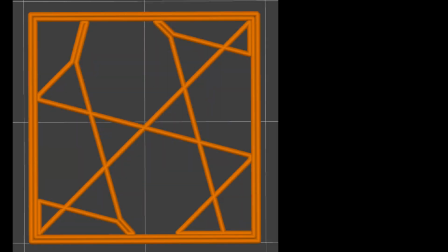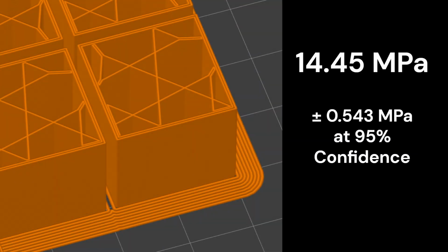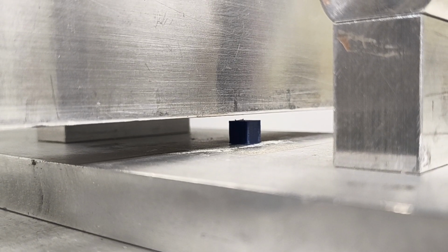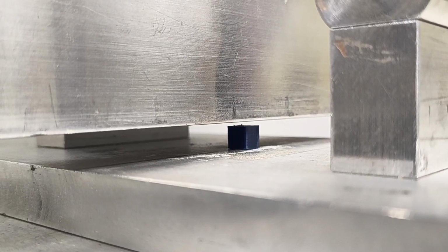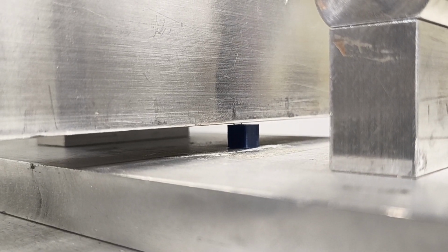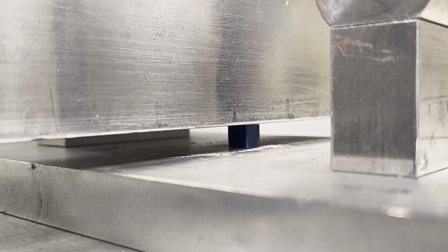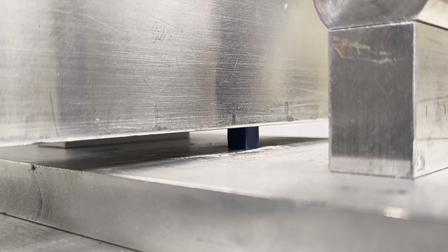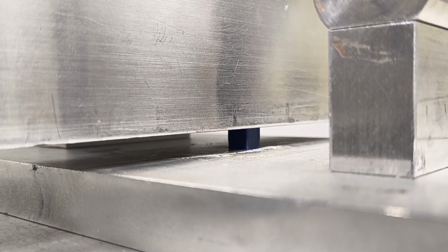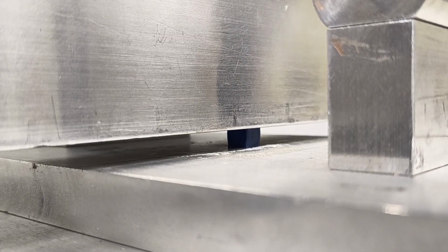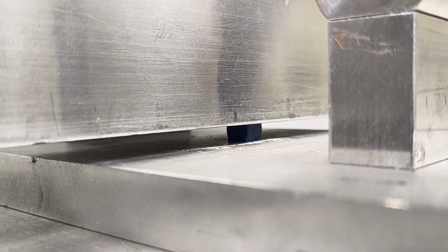Our results showed that the trihexagon infill pattern was the strongest in compression, with an ultimate stress of 14.45 megapascals along with an uncertainty band of 0.543 megapascals at 95% confidence. The experiment operation required that each sample was aligned in the center of the compression tester and not aligned with one of the holes on the aluminum compression block. However, early testing showed that minor variations in where the sample was positioned had a negligible impact on the results of the data, since the aluminum was much less likely to deform under the same load applied to each sample.